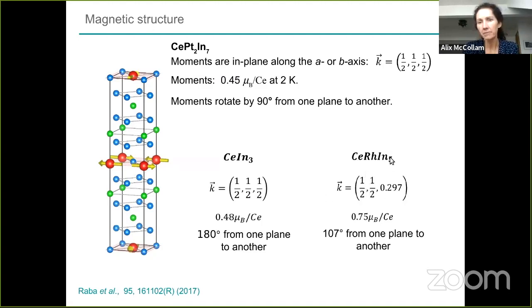In cerium rhodium indium-5, the ordering vector is slightly different. So this is incommensurate with the lattice. It's more like a spiral or kind of twisting moment. And this is more like 0.75 Bohr magnetons per cerium, and the moments rotate by 107 degrees from one plane to another. So these two are commensurate, and this one is not.